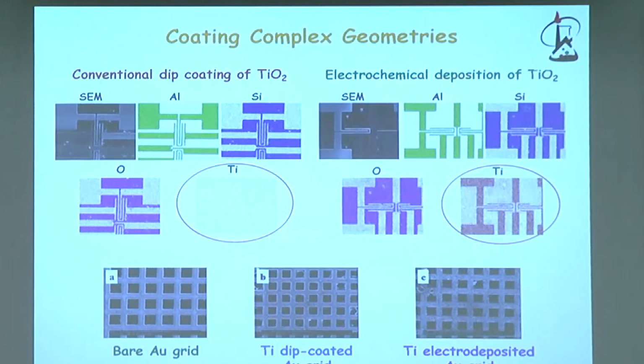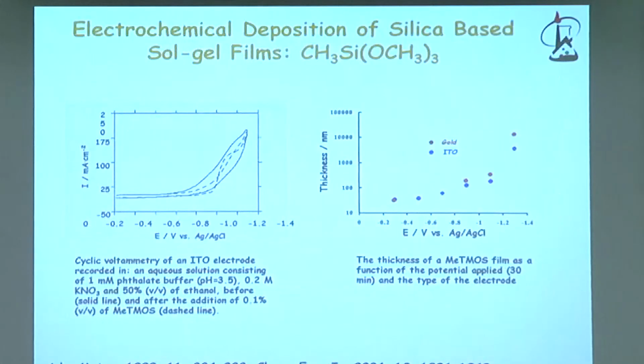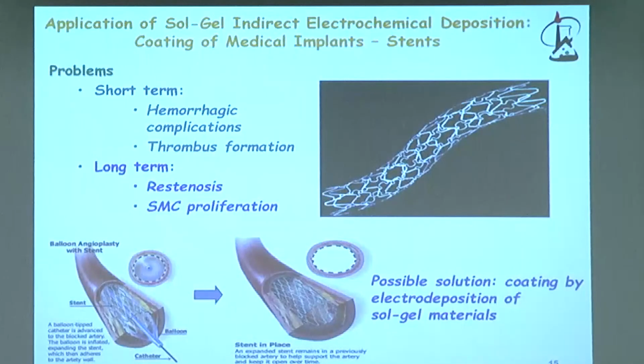And by that, as I'm going to show you, you can coat and deposit the sol-gel on very complex geometries. That's a big advantage as compared to the other methods. So this was actually the first paper we published. Nowadays, there are tens of laboratories all around the world that are using the same methodology. By the way, you can control the potential, as you can see here, and as you apply a more negative potential, obviously the gradient of pH is higher, and because of that, the rate of deposition is also higher. I'll give you only 1 or 2 examples from here.